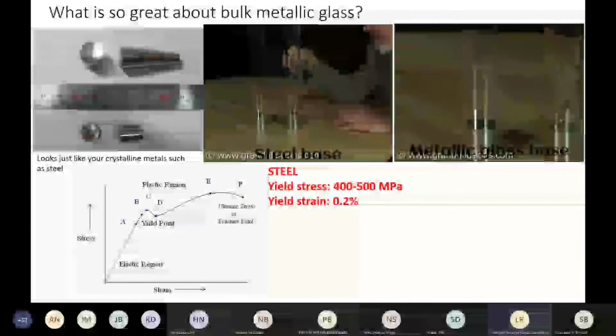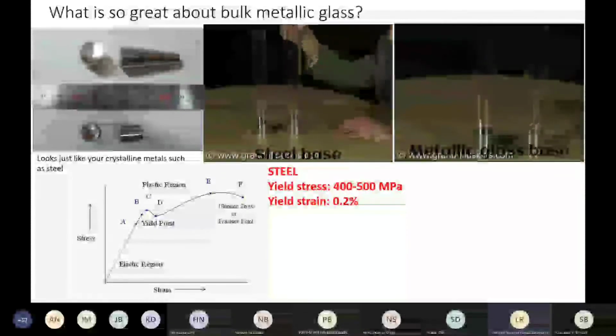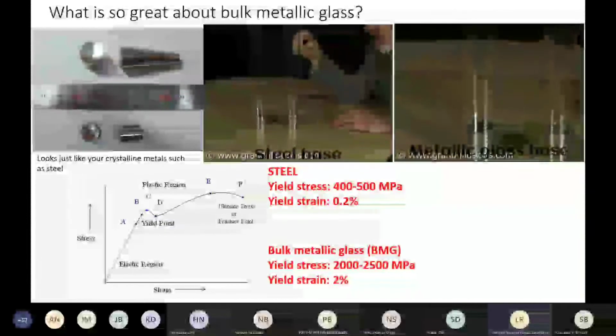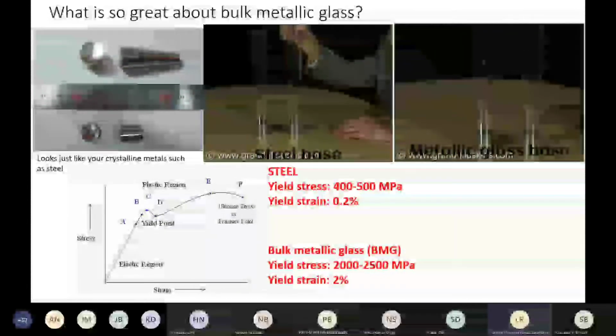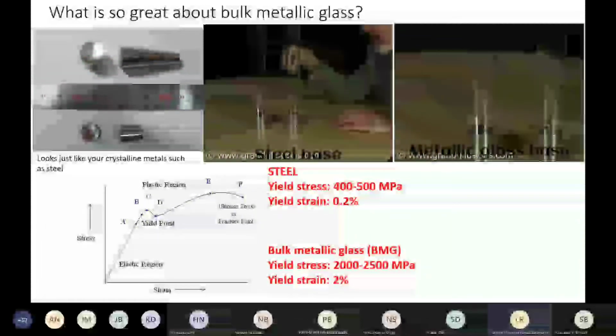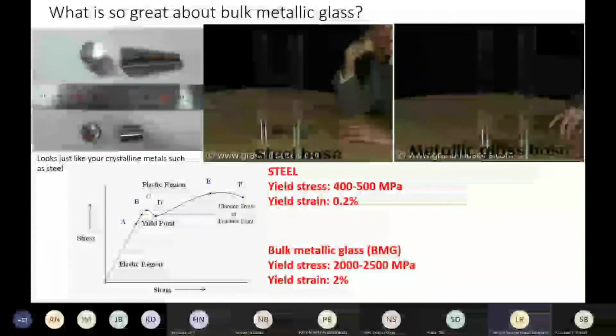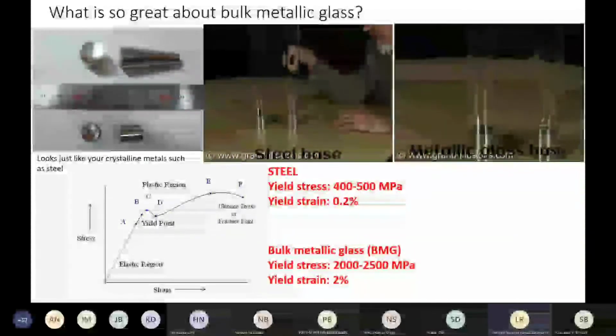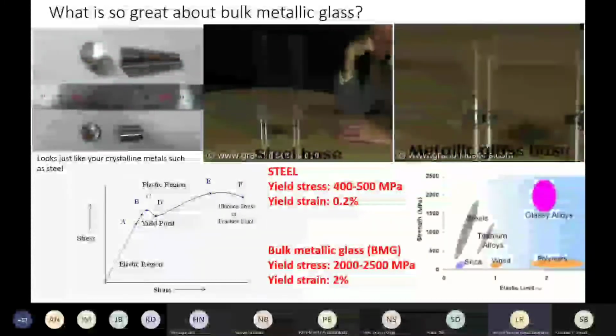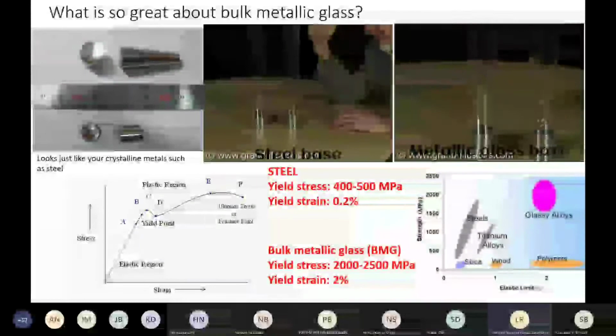We see that the yield stress of steel is about 400 to 500 MPa, and the yield strain is 0.2%. On the other hand, metallic glasses are about 10 times more strong, at least, or maybe 5 times more strong, and the yield strain is at least 10 times higher, which is exceptional for a material of this class. So as we can see, these are indeed very capable of being stronger than any other conventional crystalline material. And that is why metallic glasses have got a separate space for themselves.